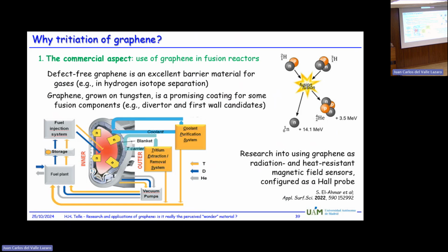And that is if you look at the system where basically the fusion is taking place between deuterium and tritium, the complete system is actually exposed to tritium. So basically that means you want to have protective layers inside your system, which actually protect your metals from erosion. And one of the ideas has been to do sort of covers of the surface with graphene, which then absorb the tritium and therefore keep it away from the lower levels. And the second one is outside the reactor, because you cannot throw this huge amount of tritium into the atmosphere.